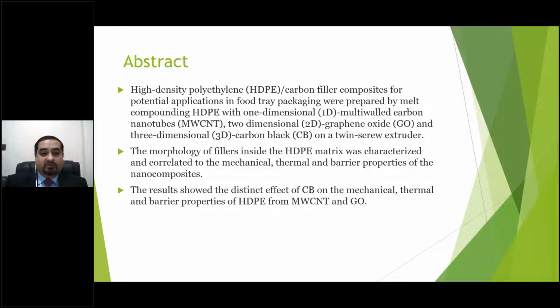So what did we do in this research? HDPE was blended by a specialized technique with various carbon fillers to produce various composites that included the incorporation of multi-wall carbon nanotubes, graphene oxide, and carbon black on a twin screw extruder. The morphology was characterized, and then it was correlated to the mechanical, thermal, and barrier properties. And the results basically showed us that there was a distinct effect of carbon black on mechanical, thermal, and barrier properties of HDPE in comparison to multi-wall carbon nanotube and graphene oxide.